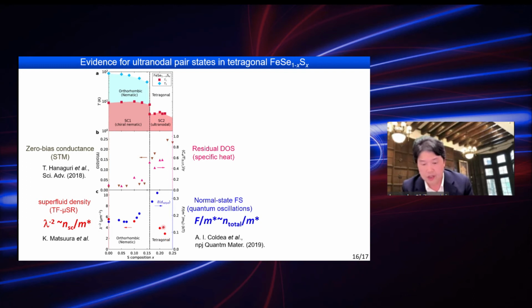So this means that if you look at the Fermi surface in the normal state, not all of it becomes gapped in the superconducting state, and there is some normal component left in the zero temperature limit. This is consistent with the presence of some kind of Fermi surface in the superconducting state.